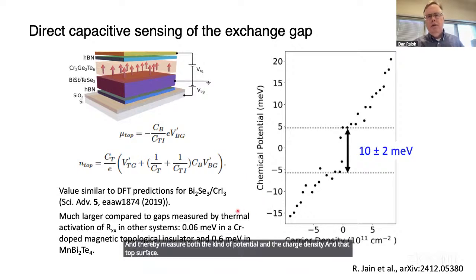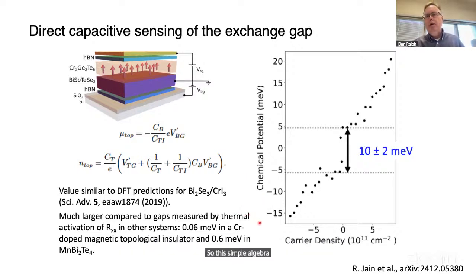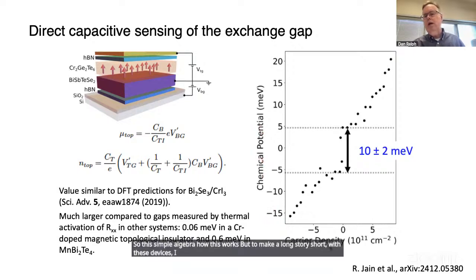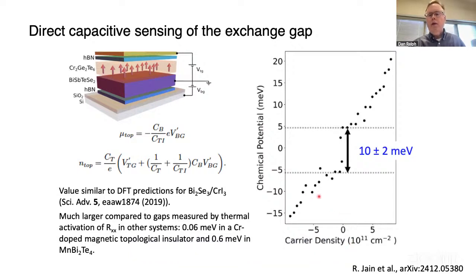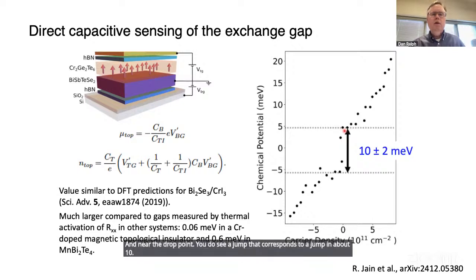The bottom surface still has a reasonably well-defined Dirac peak in the resistance. And so if you monitor the voltage required to stay at that Dirac peak as you apply a top gate voltage, you can measure the screening of the top surface and thereby measure both the chemical potential and the charge density in that top surface. There's simple algebra about how this works, but to make a long story short, with these devices I can measure the chemical potential as a function of carrier density in that top surface. And near the Dirac point, you do see a jump that corresponds to about 10 plus or minus 2 millielectron volts.